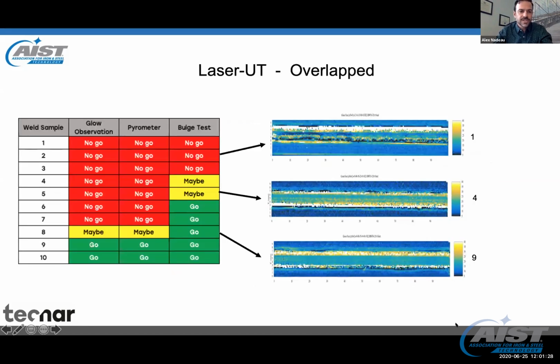So I'm not going to show these 10 welds, but on the chart here, you see there's 10 samples. Those were the 10 welds between good and absolutely bad. And they were tested by the bulge, by the pyrometer, and also by just visual observation. What is funny here is that the bulge test revealed that the threshold for rejecting based on parameter and visual observation is much higher, and that many welds can go through, and that they are actually re-welded. So that's a loss of time in a certain way.